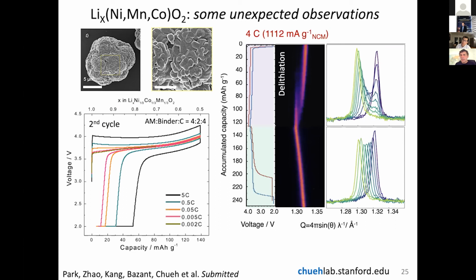But when you crank up the current, you actually get a very different behavior. So when you crank the current, so now rather than doing it over, say, 10 hours, you do it in 15 minutes, you actually see signatures of phase separation. Again, this is very strange because this material does not phase separate. There is no two-phase regime, no miscibility gap in this composition range. But if you look at the X-ray diffraction, you see a bifurcation. You see two lattice constants present at the same time, which is a telltale sign of phase separation.